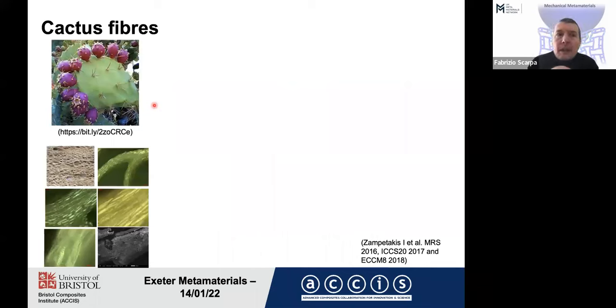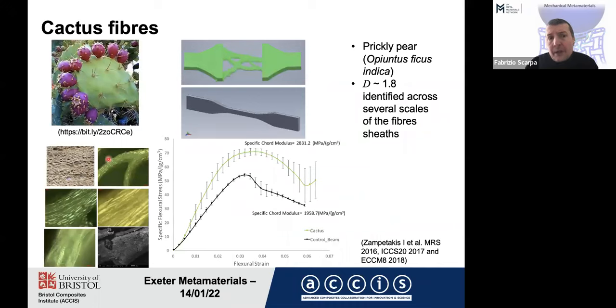At the beginning, I mentioned that we also have quite a lot of examples of fractality in nature, and I want to report this work that we have done on cactus fibers, or fibers extracted from the rackets of the prickly pear. Something that we have discovered is that if you look at the different scales of the fiber of the prickly pear, you will identify a constant fractal order around 1.8. And within a series of projects that we have also run with DSTL, we have then developed some rapid prototyping beams that were trying to simulate the fractal pattern of the cactus fibers.